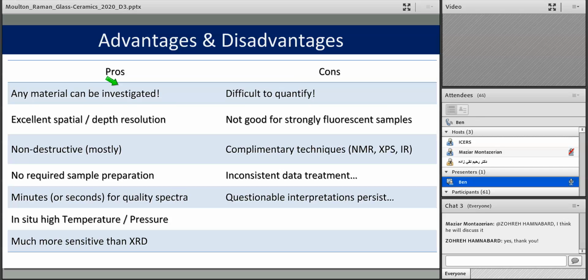There's absolutely no preparation required, although if you polish your sample, you will get a better signal to noise. You can take a very good spectra with a high power laser in seconds and for sure in minutes, depending on the nature of your sample. As I mentioned, you can use in situ devices for reaction cells, pressure, temperature. So long as you have a window that allows visible light to pass through, you can do in situ Raman measurements.